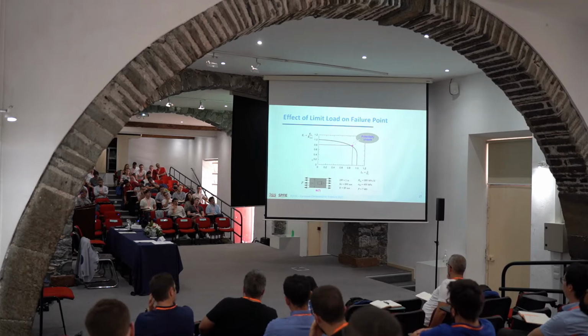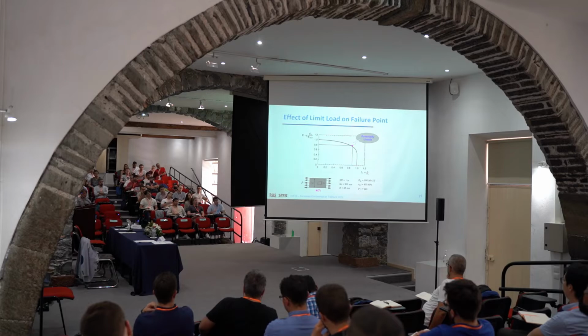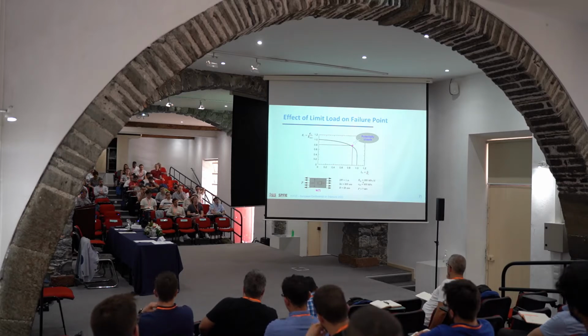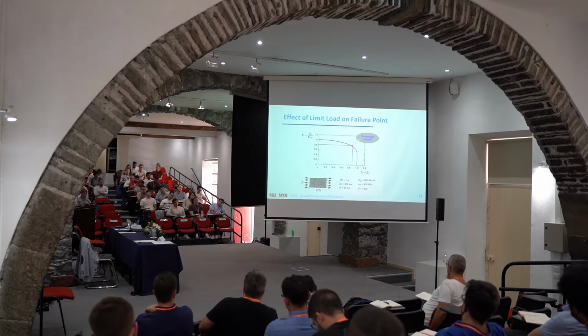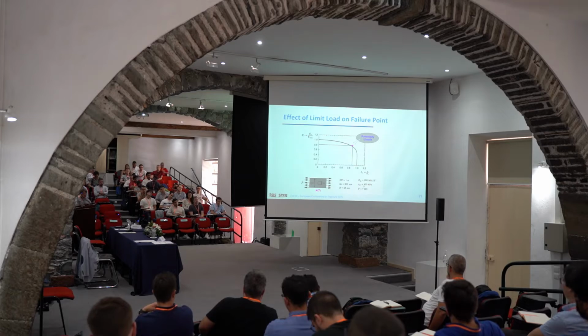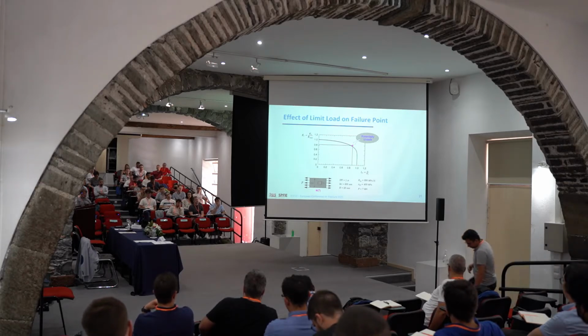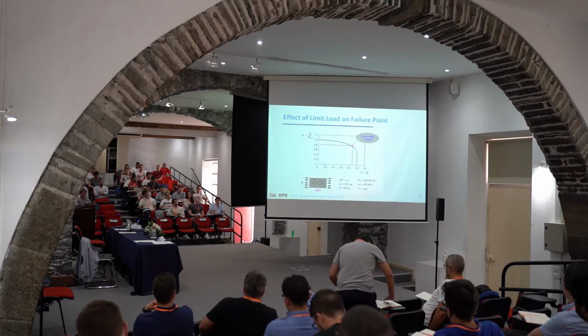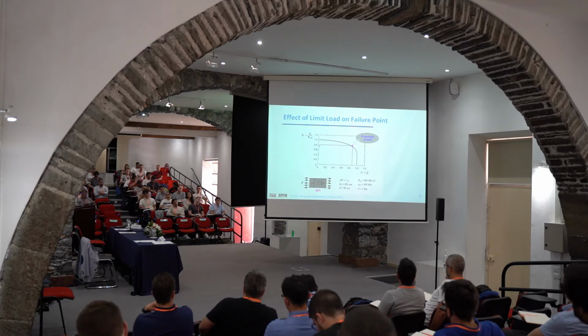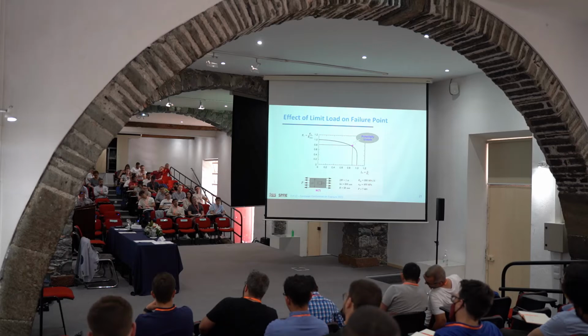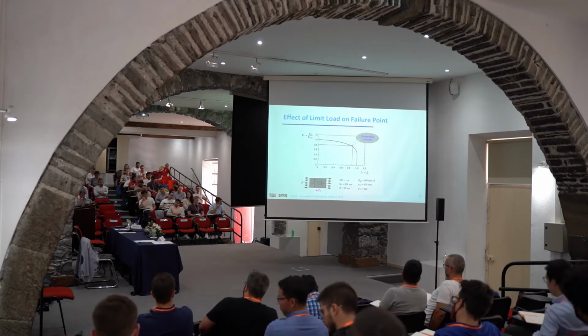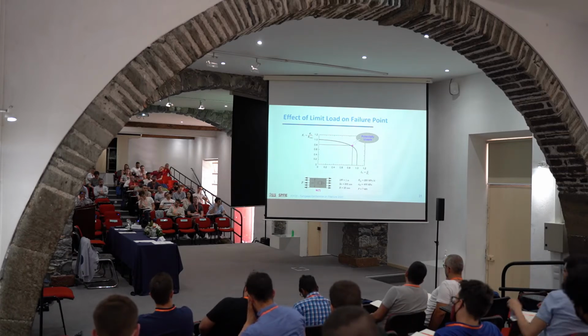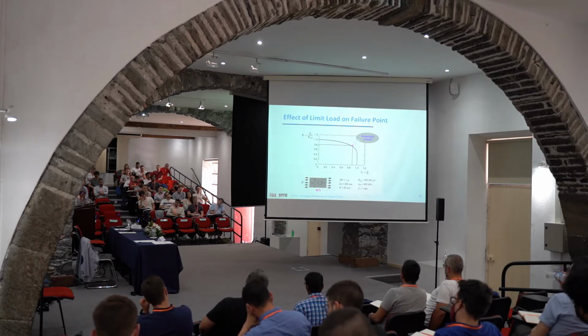Okay, so if you conduct a very plain, simple fracture mechanics analysis, here are the specimens. The KIC value, the fracture toughness value in the last regime, is 200 megapascal square root meter. The yield stress of the material is 400 megapascal, and the applied load is 7 meganewtons. So if you do the calculation, you find out that from the fracture side, your structure is safe. Of course, if you don't consider any safety factor, I just mean that your driving force is less than your toughness. Of course, in the real world, we would take into account some safety factors for uncertainty, but let's forget about uncertainty. So fracture does not occur.